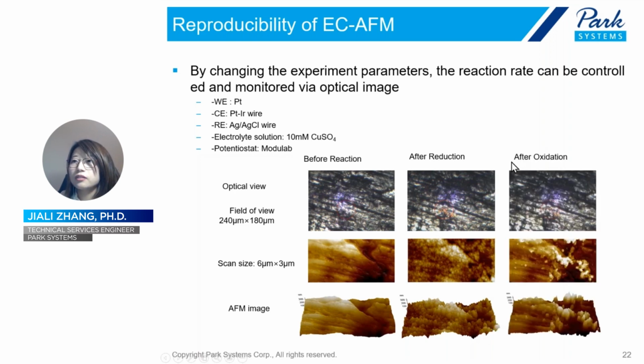And by doing the oxidation reaction, you will find that the brownish covered area diminishes and becomes smaller, as the copper domains decrease in this AFM image. So the optical view of our built-in optical microscope gives you the microscopic evidence, and the AFM gives you the nanoscale evidence that this redox reaction is happening.